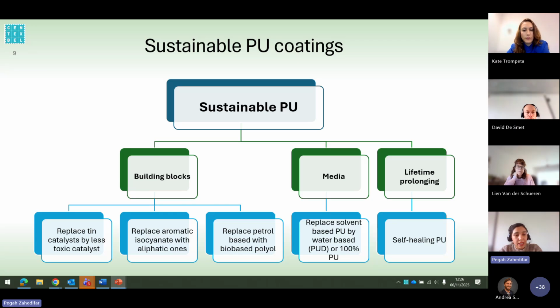For example, we can replace the catalysts that we are using with safer or less toxic ones, or we can replace the aromatic isocyanate with aliphatic ones, which are less toxic, or we can replace the building blocks with more bio-based building blocks like the polyol, as I mentioned. Or we can change the media that we are synthesizing the polyurethane in with, for example, the water-based media that was mentioned earlier. Or we can extend the lifetime of the polyurethane.